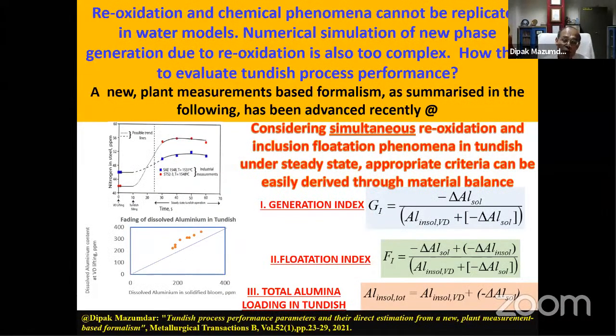So, when you do Tundish processing, look at the figure here. This is the dissolved aluminium content in the Tundish. Dissolved nitrogen at the VD lifting station for two different grades is shown here. As you can see, the dissolved aluminium content shoots up as the Tundish filling starts, and then it attains a steady state.